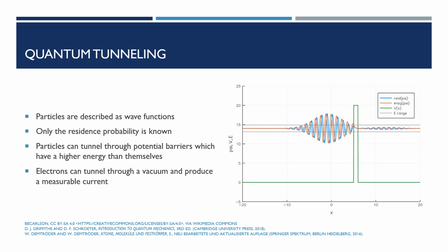The first experimental verification of tunneling was made a quarter of a century before by Ivar Giaever of the General Electric Company, where a thin, rigid insulating layer was used to separate two electrodes. The gap between the electrodes was small enough to allow the electron clouds to overlap slightly. A potential difference between the electrodes, induced by applying voltage to them, causes electrons to flow from one electrode to the other.